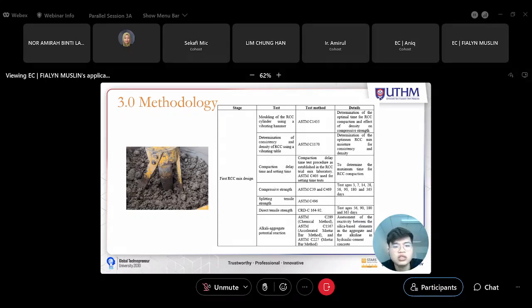And also setting time is of most concern because RCC is compacted layer by layer. That's why the setting time should be identified for the site construction. And then the alkali aggregate potential reaction is also something we should be concerned about to determine the durability of the concrete.